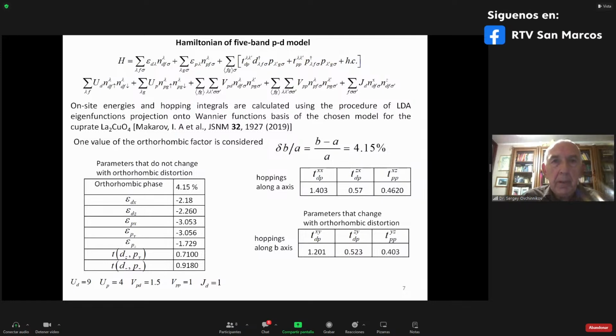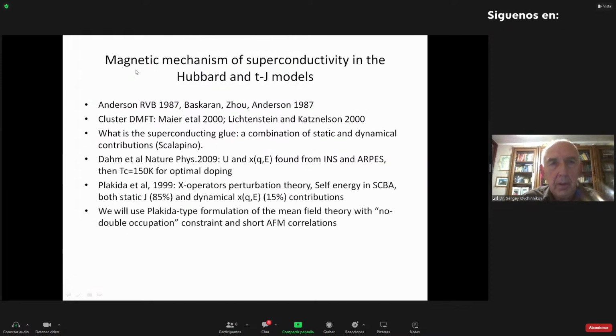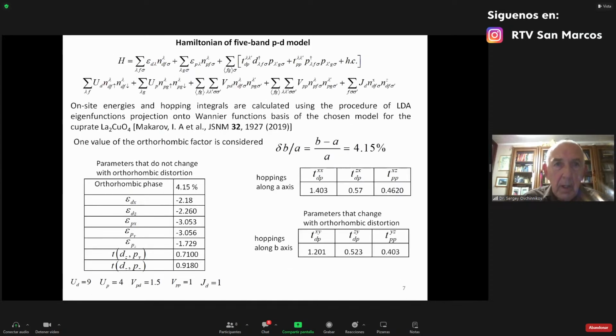Okay, then we come back to the 5-band pd model for cuprates. This term corresponds to d holes on the copper. Lambda is the orbital index; lambda corresponds to 2 orbitals for the copper, dx2-y2 and dz2 orbitals. Also 3 orbitals px, py, and pz for oxygen. Hopping between copper and oxygen, just like in the tight-binding pd model, and also all Coulomb interactions inside the copper, Coulomb Ud, Coulomb interaction inside the oxygen, Up, Coulomb interaction between copper and oxygen, between oxygen and oxygen, and finally the Hund exchange interaction inside the copper.